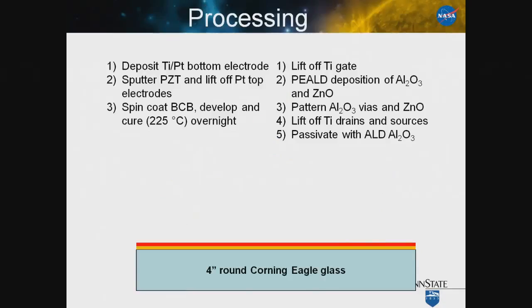The approach that we've taken to do this is to start with a 4-inch Corning Eagle glass. This is basically a display glass. The reality is those are available in up to 10 meter square segments, so gracious area if we ever scale to that size. We deposit on that the bottom electrode for the piezoelectric array, and then the piezoelectric with its electrode stack. And so we basically sputter deposit the lead zirconate titanate, crystallize it, then sputter deposit the top contacts using a liftoff approach to do the patterning of the platinum. On the entire stack, we spin coat a layer of benzocyclobutene, which is a photopatternable polymer.